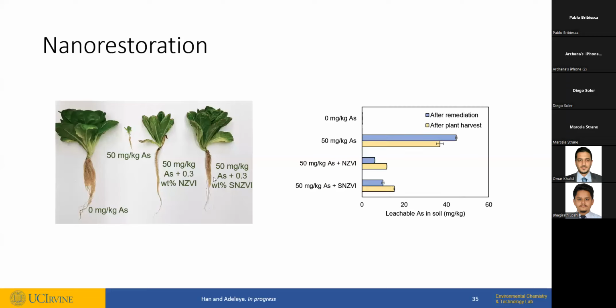On the other side, we also looked at the soil, the amount of arsenic that is leachable before the plant was grown and after the plant was harvested. And we think we found something really interesting there. So in this case, there is no treatment. You can see initially there is this much leachable arsenic. And in the second part is when we have harvested the plants, and you can see that the arsenic concentration that is leachable decreased. Any guesses as to why that may happen?